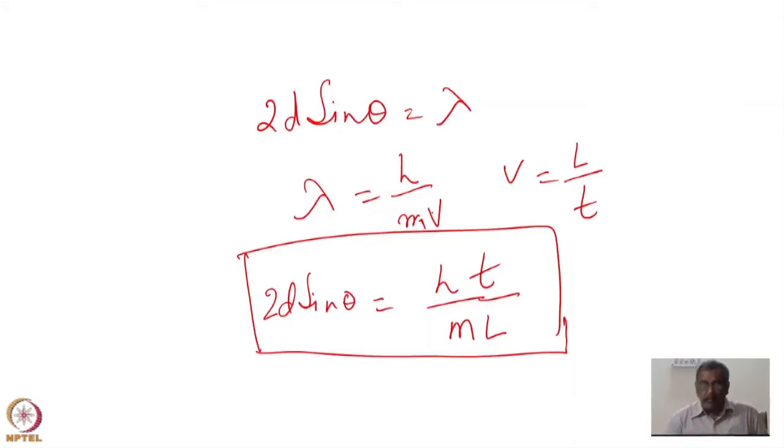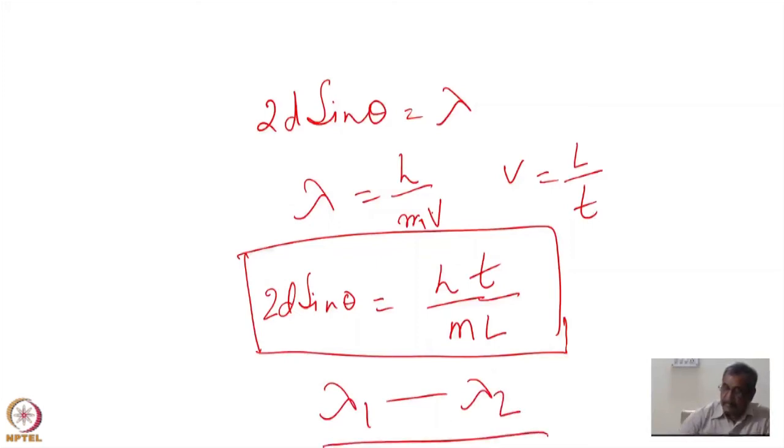So in the case of pulse sources, we don't try to monochromatize the source. We choose neutrons in a pulse, but of course we cannot take all the neutrons. So there is something called choppers, a combination of choppers, which will allow a certain range of wavelength for our application. And after that, we do time of flight spectroscopy using this formula.